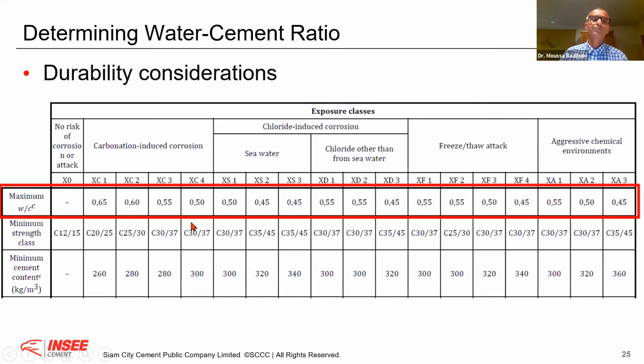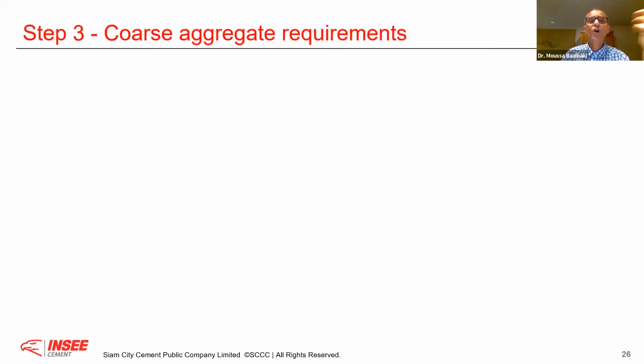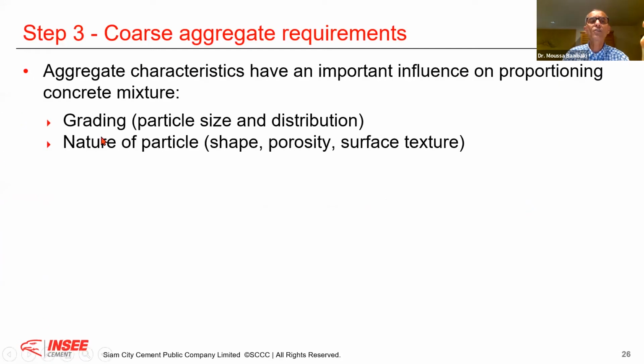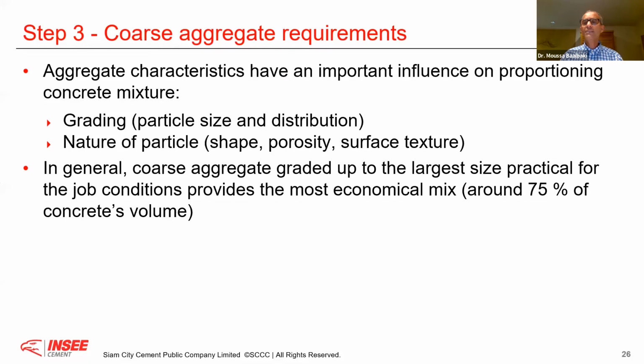Okay? Now, step 3 is the coarse aggregate requirements. The coarse aggregate requirement is important here because you need to consider the grading, the nature of the particles. That is important if it has the shape, the porosity, the particle size distribution, the particle size. And at the same time, we should keep in mind that when you have a coarse aggregate graded up to the larger size, practical for job condition, that provides the most economical mix because around 75% of concrete volume is aggregate.